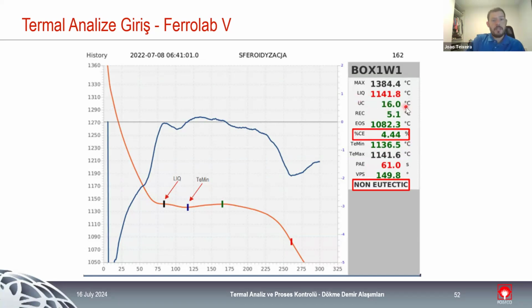We can see the undercooling, and undercooling is the difference between a theoretical minimum and the reference point. So the reference point is, as I mentioned, the stable temperature, close to 1151, 1152. And if you remember, we discussed that the inoculation step should always occur between the stable and the metastable. So between 1151, 52, and 1120, 25. So the minimum point during eutectic is the theoretical minimum. So if this point is above the metastable temperature, it indicates that we have a high percentage of success during the inoculation step. And it is what's happening here.